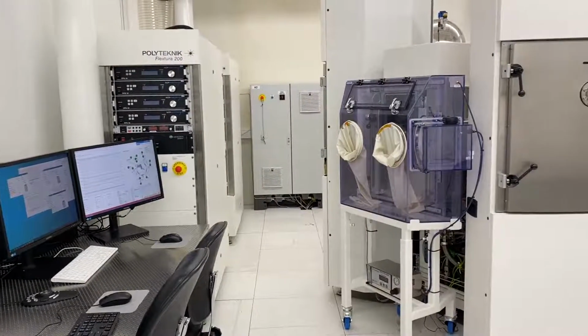And because we have these retractable targets as well, we can place the target inside in the very thick of this plasma, where it's a very high plasma density and you get a high growth rate. Or we can also deposit a little bit more outside, where you have a much lower growth rate. That means that you can have these very reactive species and you can combine it with a low deposition rate. What that means is that when you have adatoms that have come to your sample substrate, they have the time to move around, they have enough energy to move around and find the least energetically favorable position. And this allows us to do epitaxial growth.